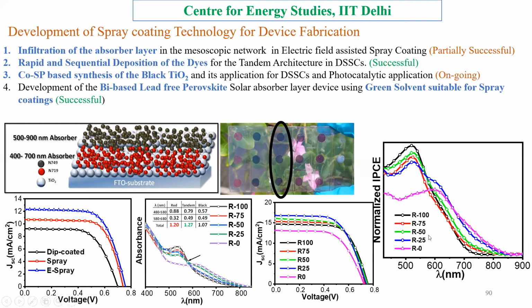So I can see that R100 is a red dye. When I am taking all red dye, absorption is very good at the 550 nanometer region, but not good at the 400 to 700 nanometer region. But when I keep on adding and making the layer of black dye, we see that the absorption in the 600 to 700 region improves, overall 400 to 700. And I can get one optimum concentration, because obviously if I am putting more black dye, I have to put less red dye. So this blue curve is one optimum concentration, R25, where I take 25% of the red dye and 75% of the black dye, and we can see that now I can have absorption at both regions. 550 also I am absorbing, 650 absorbing, overall absorption improved from 400 to almost 650 nanometer region.